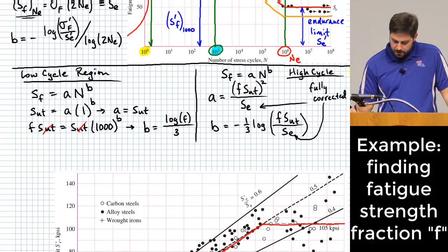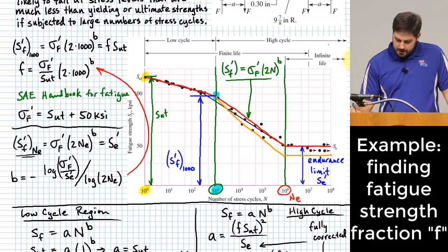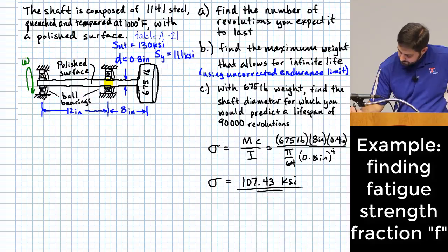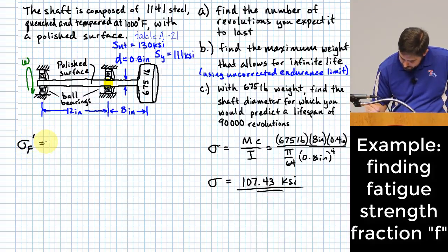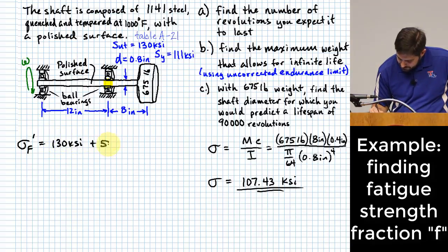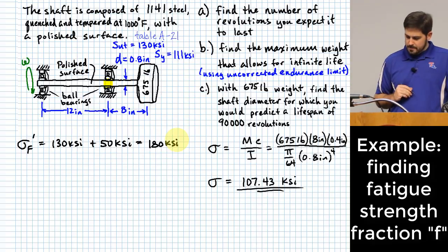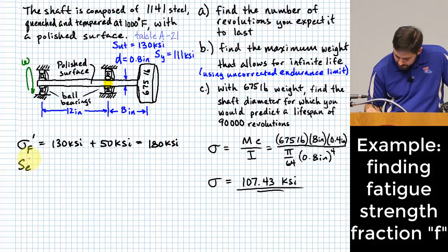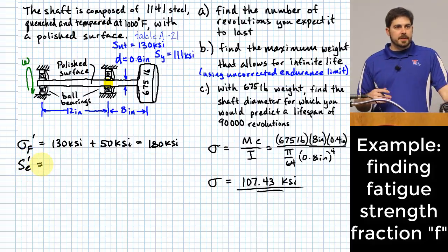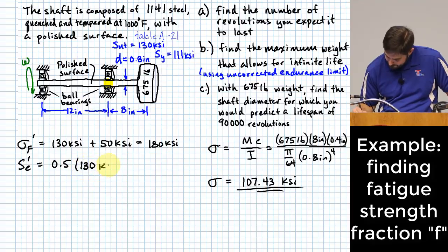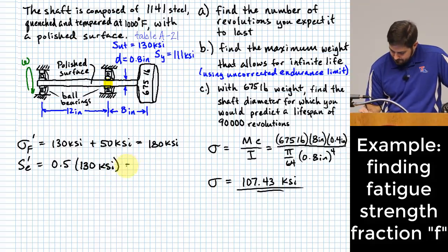That'll be the next thing we do, is we have to run through this technique that I just set up here. All right? So the first step that we will do, I guess, is we will figure out the fatigue strength coefficient. It's 130 KSI plus 50 KSI. All right. The next thing we'll do is figure out S sub E prime. Right? That's our uncorrected endurance limit. It's going to be equal to 0.5 times what? 130 KSI. And that gives us what? 65 KSI.